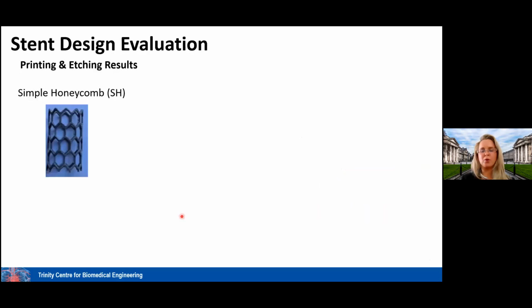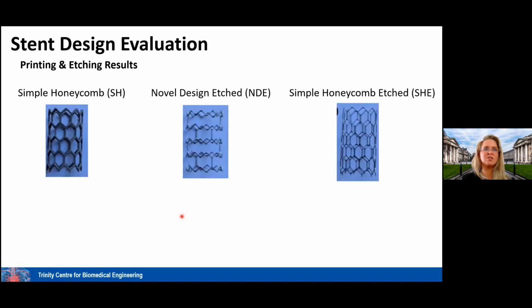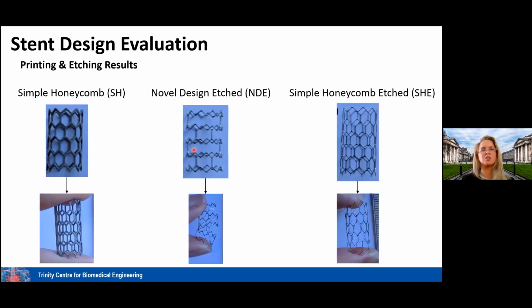So looking at our printing and etching results, what you can see here is from our simple honeycomb to our novel etched and to our simple honeycomb etched. Even just qualitatively, if we try to bend the ends of them and look at their bending stiffness, you can see the open cell structure. Even intuitively, you would see that the open cell structure should allow greater conformability to a curved vessel.